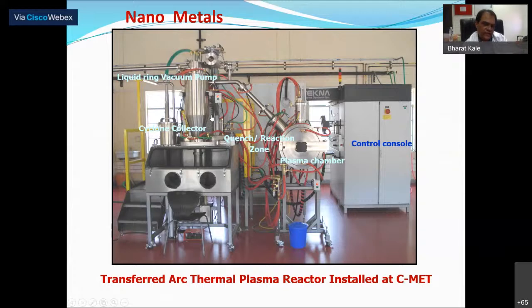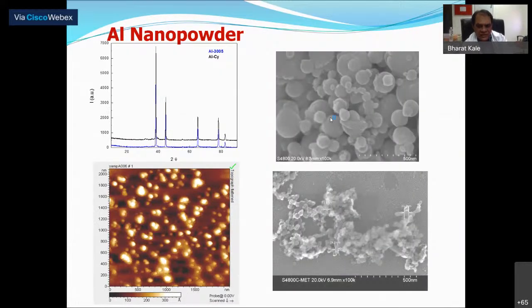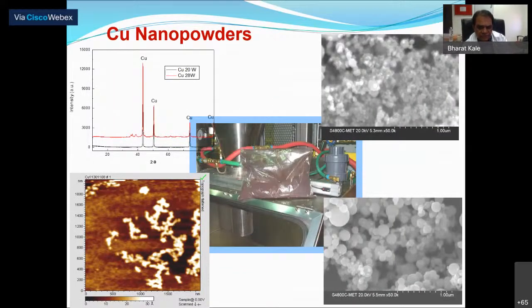This is a 5 crore equipment we have installed in our laboratory, and it is very useful to our strategic sector. This is aluminum powder. Though you see bigger balls here, they are nothing but hollow balls, with very small particles deposited on them. These are the aluminum nanoparticles we have made with the plasma reactor. This is copper nanoparticle, very small, up to 200 nanometer size scale. Many nanoparticles are deposited on this ball, and inside there is a ball here also. The advantage of this plasma reactor is we can get a uniform particle size like this.